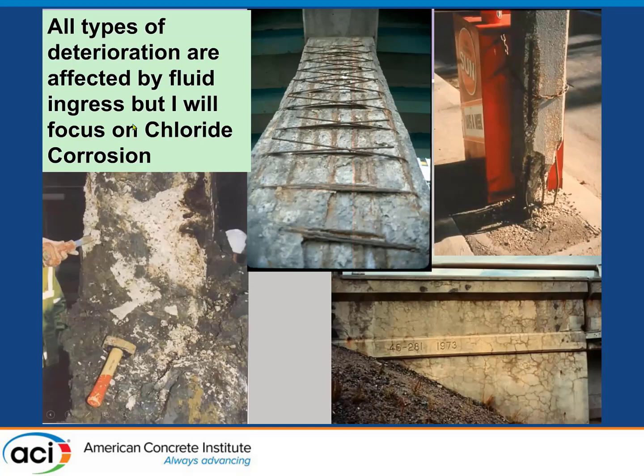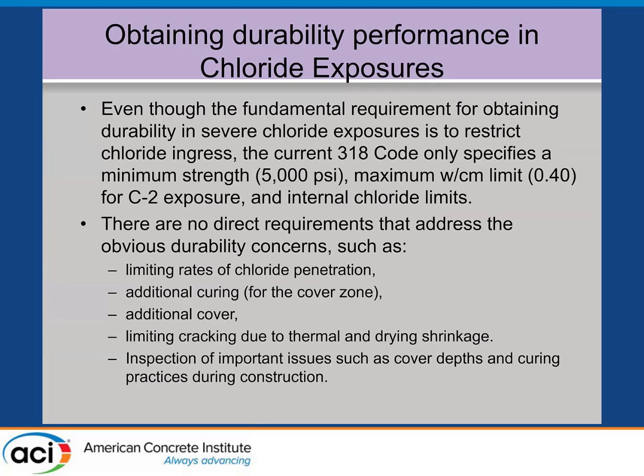Now, there's all kinds of deterioration out there that affects durability. And all of them are affected by fluid ingress rates. I'm going to focus just for the talk on chloride corrosion to save time. So even though the fundamental issue with preventing chloride corrosion is to restrict chloride ingress to the reinforcing steel, the current 318 code only provides a strength requirement and a maximum water cement ratio limit. And there's only one exposure class for all chloride exposure, C2. There's no direct requirements to address the obvious issues that one would think of, like limiting rates of chloride penetration.